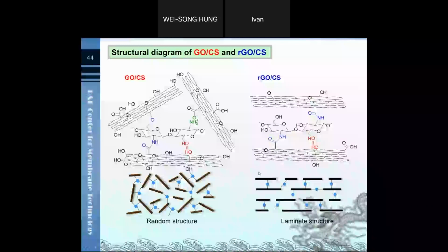The graphene chitosan membrane structure is due to the negative charge of the graphene oxide and the positive charge of the chitosan. Blending them forms a strong ion complex, which causes aggregation. After the graphene oxide is reduced, the weaker negative charge of the reduced graphene oxide inhibits the ion complex formation.